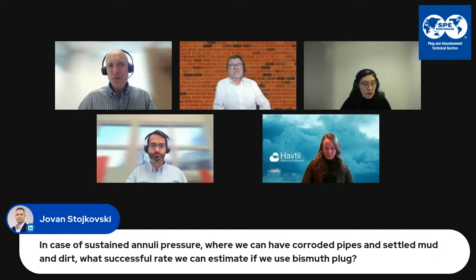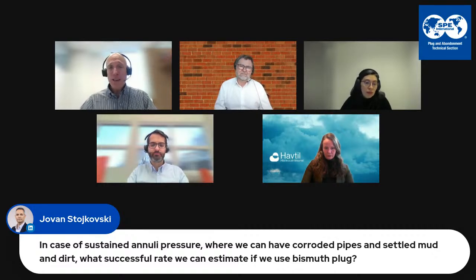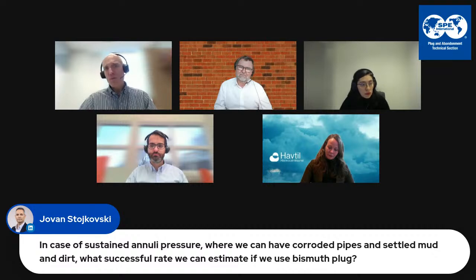And I think in response to the question by Jovan, based on what you showed and presented, Martin, if you create a very good window for placement of the plug by section milling, then you create the opportunity for success. If you were trying to place bismuth in an annulus through perforations, then you would need to make sure they're clean. You would need to make sure that annulus will receive the bismuth in better conditions. It might be more challenging for the application, which then calls into question the success rate.